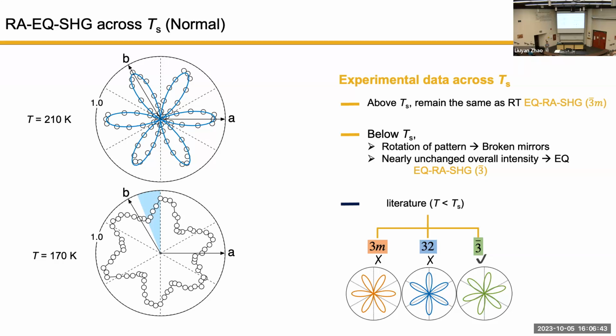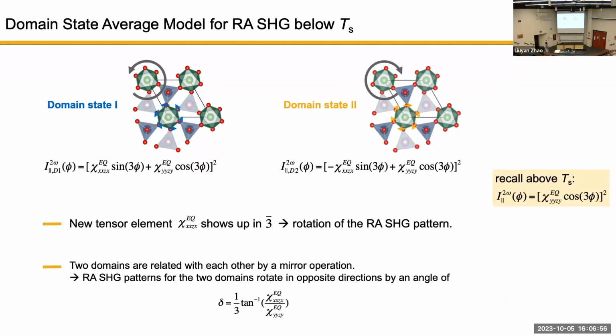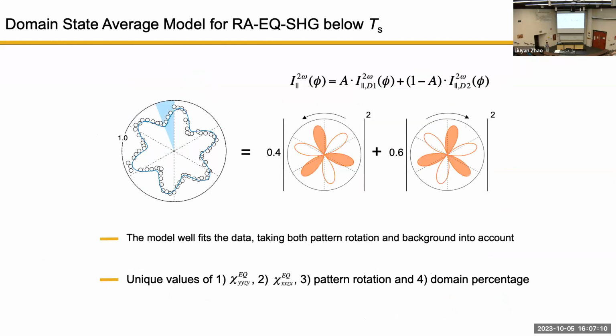But simultaneously, from this simulation, we will see that the valley goes to 0 perfectly, while my data actually has a huge background. So why is that? The reason is because we said there are two equal possibilities of the state once you go across this temperature. You rotate this way or you rotate this way, opposite ways. So the reason for us to see the background is really because the signal was so low. So then we had to blow up our beam to survey more domains to accumulate my signal.